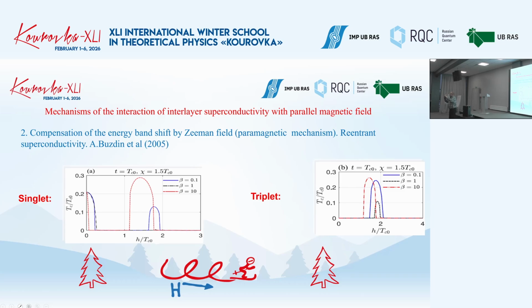It's a sort of compensation of the change in the symmetry of the electronic spectrum. And because of that, it is possible to get reentrant superconductivity. We, of course, obtain this theoretically, but experimentally this reentrant behavior has not been observed, which probably means that the parameters which require this kind of behavior do not correspond to these particular structures.